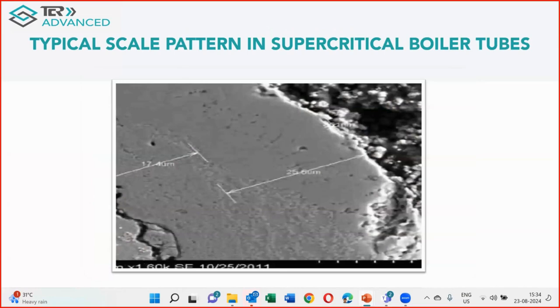See, supercritical boilers are mostly designed for once through, which means there is no steam drum in the supercritical boiler. In the supercritical boiler, the material used in most of the tubes is very high grade. So there, instead of a magnetite layer, you will form a chromia layer. Chromia is a chromium rich oxide layer. So these must be analyzed only on an electron microscope. And it is said that any thickness above 40 or 50 microns reduces the efficiency of the boiler drastically. So characterization of these layers is very, very important.